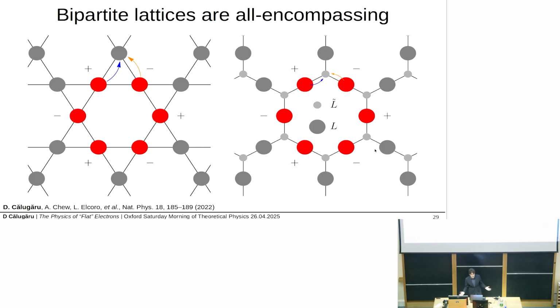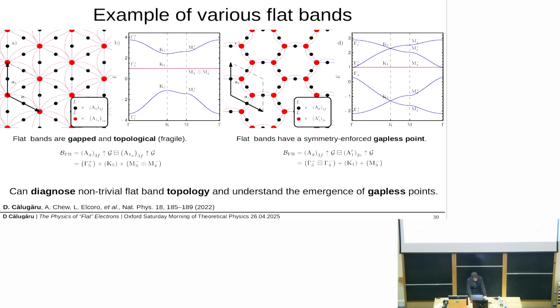And the reasoning is very similar, right? But now, with this sort of bipartite formulation, I can get all these results without ever invoking any sort of hopping whatsoever. And in this example here, I'm actually building two toy models of flat bands, right? So in both cases, I take my big sublattice to be made up of s orbitals on a Kagome lattice, right, these black dots, and then I vary the contents of the small sublattice.